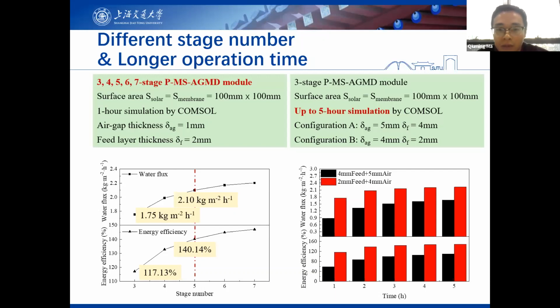And for longer operational time, we also tried it because all of the above operation were just 1 hour. And with the prolongation of the operation time, you can see the performance first augmented a little bit, then tend to stabilize. That's because the whole device, the MD process, they have an initial stage, because at the beginning the temperature of all the feed layers are just the same as the outside surrounding seawater. And with the solar income, the temperature is going to reach a certain point where the MD process can happen. So with longer operational time, the impact of the initial stage can be lessened. And that's why we can see this trend similar to the stage number.